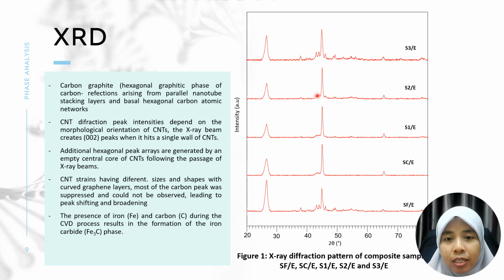And the next higher peak comes from the iron carbide. So the presence of iron and carbon during the CVD process results in the formation of iron carbide Fe3C phase. So this is actually the Fe3C phase.